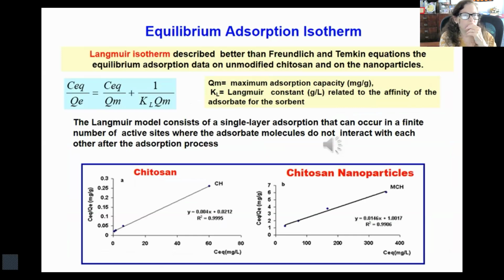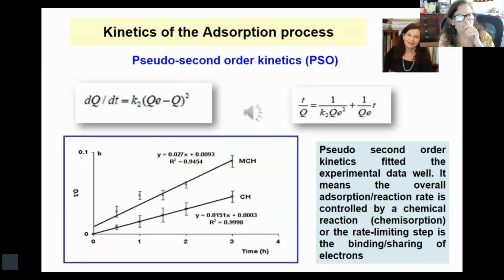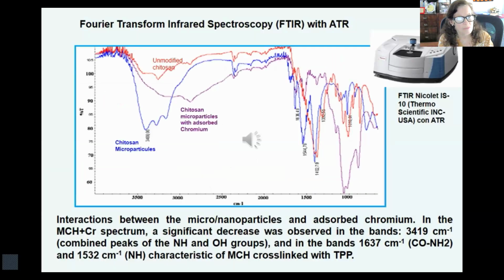As can be observed in the figure, equilibrium adsorption isotherm for chitosan and chitosan nanoparticles was satisfactorily described by Langmuir equation, where Qm is the maximum adsorption capacity and Kl is the Langmuir constant. Pseudo second-order kinetics fitted the experimental data well. It means the overall adsorption reaction rate is controlled by a chemical reaction or chemisorption. That is, the rate-limiting step is the sharing of electrons. Interactions between the micro and nanoparticles and the adsorbed chromium were analyzed by Fourier transform infrared spectroscopy.